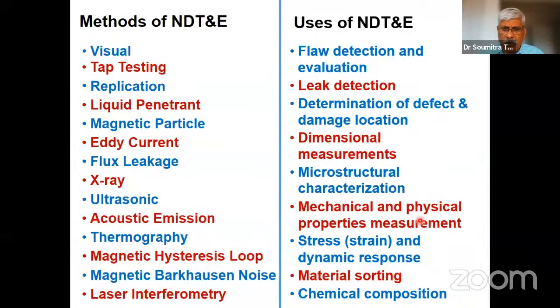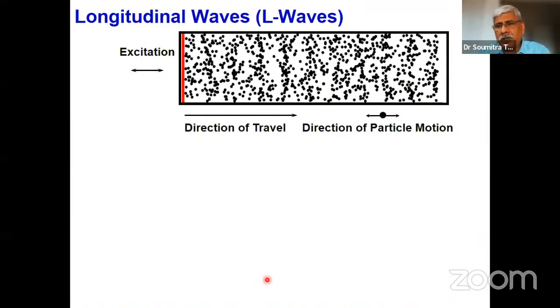But all these, the lower half of this, are specialized applications which require continuous development, which often require developments which are tuned to particular situations, particular material systems, particular type of damage. So it requires calibration at the back. And that is where a lot of research and development is necessary. And that is what we try to do at NML. And these often use techniques like magnetic hysteresis loop, magnetic Barkhausen noise, etc. But it often uses simple non-destructive ultrasonic techniques, maybe in a new avatar, non-linear ultrasonics. So, ultrasonic is very popular.